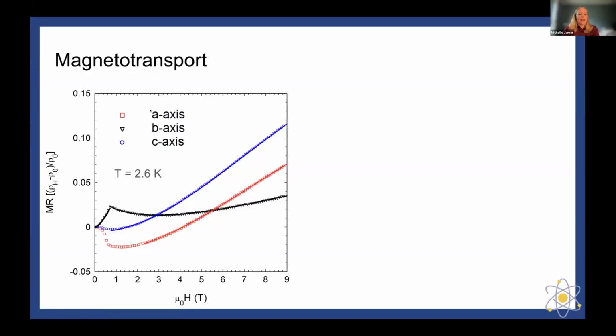And what we have is the A-axis is in red, the B-axis is in black, the C-axis is in blue. And at T equal to 2.6 Kelvin, where we're in that ferromagnetic state, what we see is a sharp increase of the magnetoresistance before 0.75 Tesla. And then we start to see kind of like a parabolic type curve. The C-axis kind of dips down to slightly below 0, but then it increases cyclotronically. And then the A-axis looks pretty similar to the B and the C kind of combined.